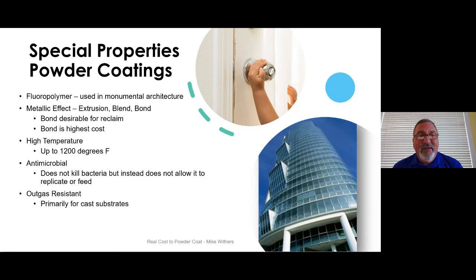Outgas resistance, that is something that really can impact your cost. So if you're painting castings, especially nowadays, castings have a lot of recycled metals in them. And even the process of creating the casting will trap gases down into the cast component you're trying to paint. And so those gases like to come out at the temperature we like to cure powder. And so you get pinholes, and then you have to go back and rework those oftentimes. We can build into a formula outgas resistance to help with that. And so there's another case where you wouldn't use an outgas resistant product unless you have a substrate that is subject to outgassing.